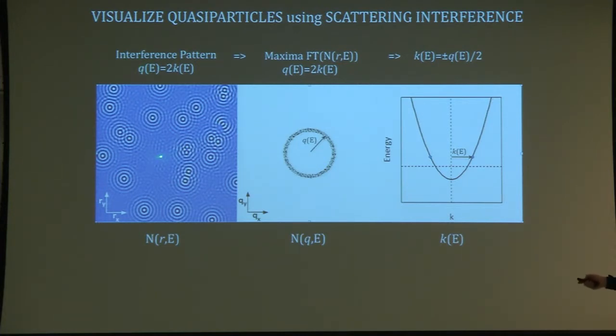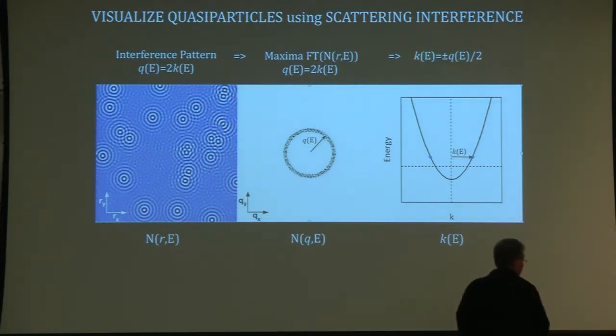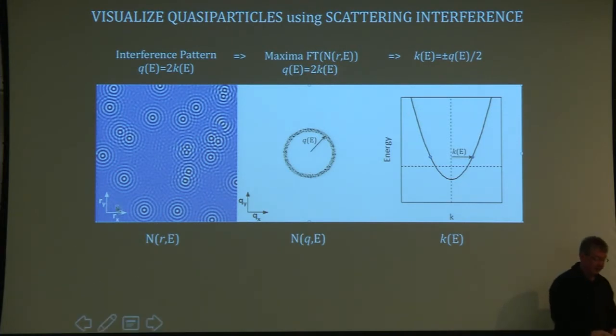So you could take the Fourier transform of an image of the density of electronic states. It would tell you the q vector of all these incoherent scattering interference patterns. That q vector is related to the k vector by this simple equation in a parabolic two-dimensional band. So now, by using energy resolved STM, let's see if this works.